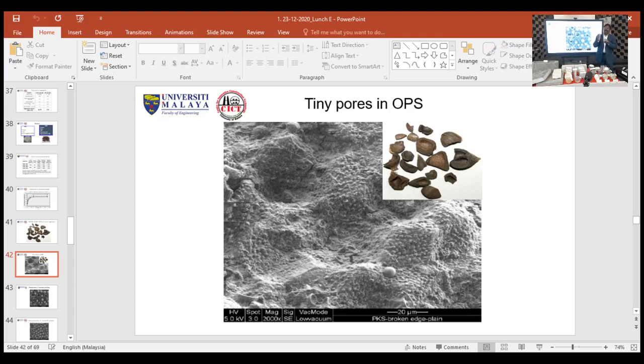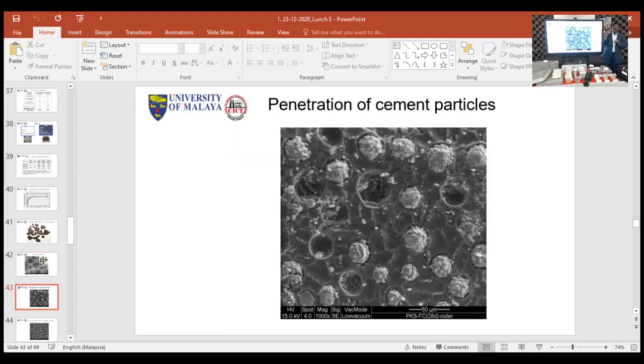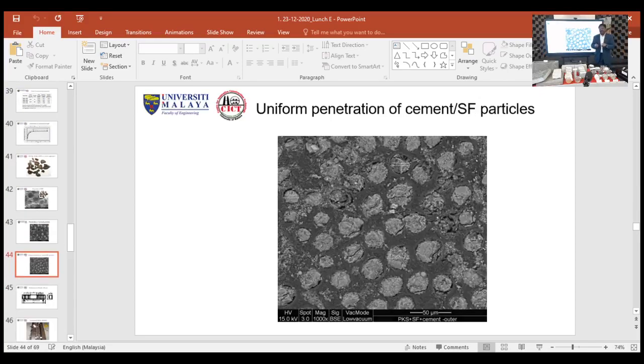We tried to use only the plain cement, and we found out that all the pores that you see here on the screen and what you see in my hand, actually the same surface, less than 20 or less than 30 micrometer, the cement particles are bigger compared to silica fume, so it cannot infiltrate, you see that there are voids. Whereas if you look into the next image, when we added the silica fume with the cement, most of the pores within this concave convex surface are already filled with the so-called binding particles of silica fume, because silica fume is very fine, 100 times finer than the cement particles. So that led us to the next stage of fabricating the beams.